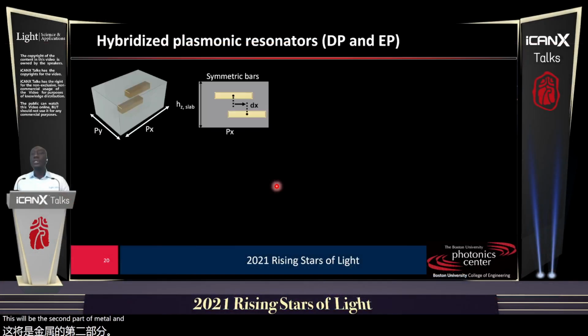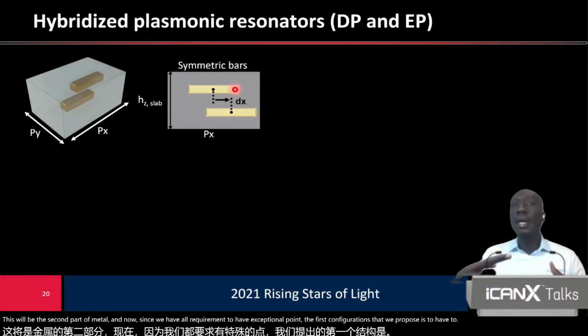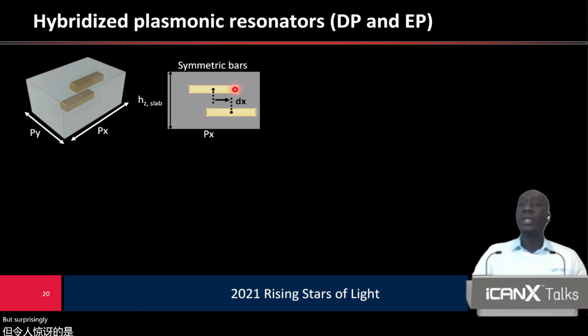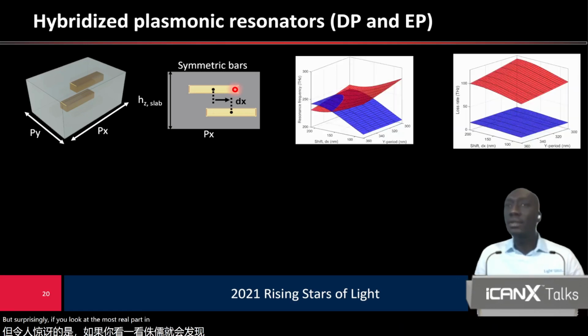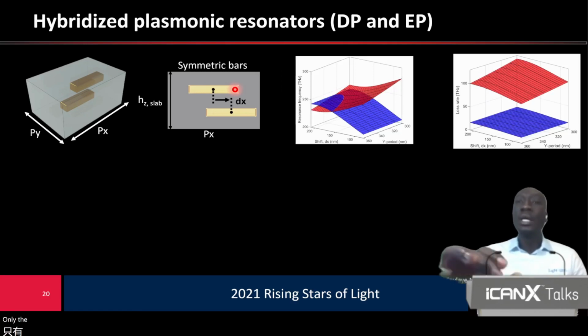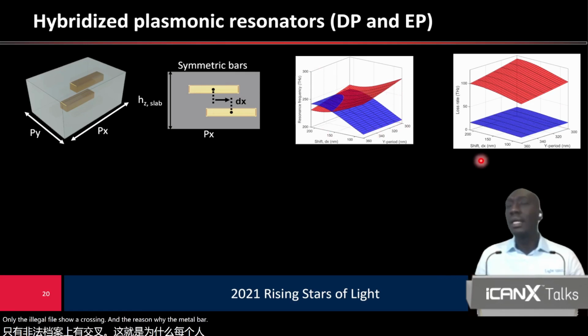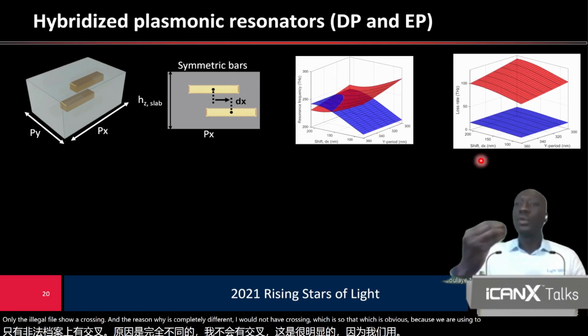Now, since we have all the requirements to have an exceptional point, the first configuration that we propose is to have two bars with the same size embedded in a dielectric. But surprisingly, if you look at both real part and imaginary part as a function of the two physical parameters, only the real part shows a crossing and the imaginary part is completely different. We don't have a crossing, which is obvious because we are using two modes with opposite symmetries.